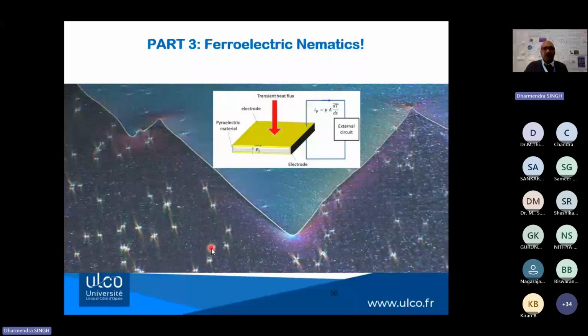The third part is associated with ferroelectric nematics. As I told you, in the current technology we use solid ferroelectrics, which have a spontaneous polarization of microcoulomb per centimeter squared. The soft ferroelectrics have their spontaneous polarization in the order of nanocoulomb per centimeter squared. However, in 2019 and 2022, a new phase was developed that is called the ferroelectric nematic. In that ferroelectric nematic, the spontaneous polarization value is found in the order of microcoulomb per centimeter squared, which is equivalent to solid ferroelectrics.